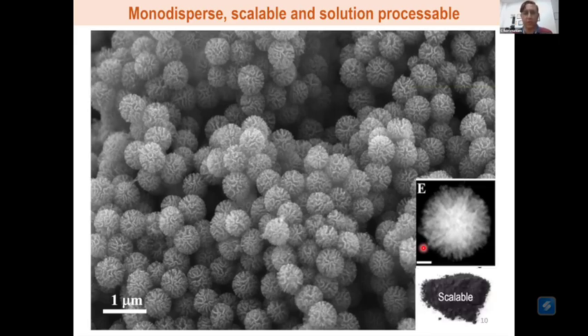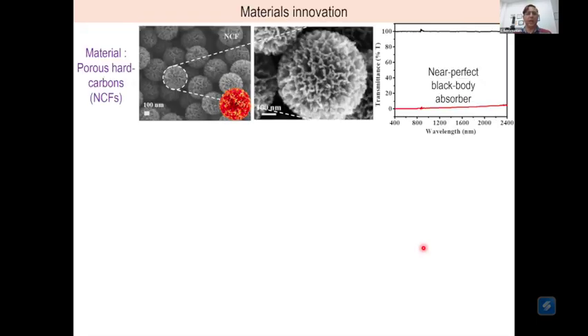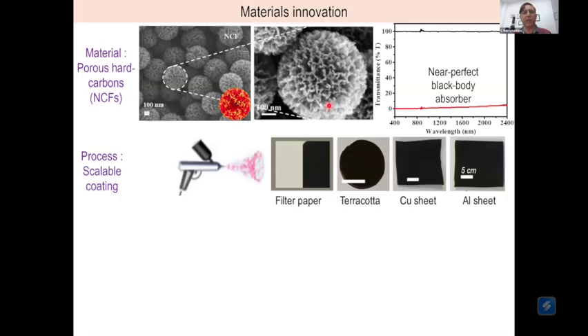And we have optimized the conditions so that we can make this on a very large scale. We can make kilograms of this in one batch, and it's extremely monodisperse and solution processable. So what do we do with this? When we make it, we get it in the form of a solid powder, which we then process and make in the form of a dispersion or a paint. This gives us the flexibility and versatility to coat it on a lot of different substrates.